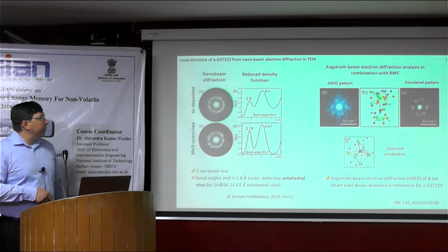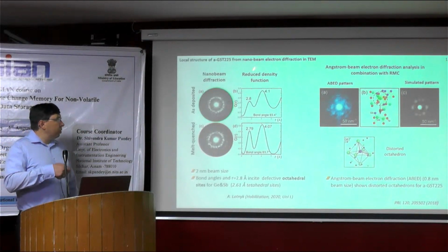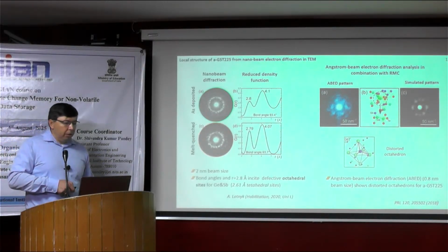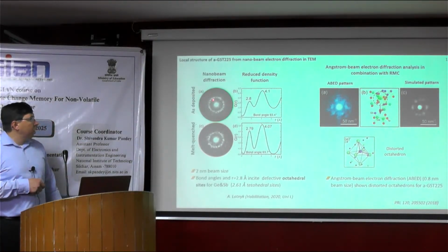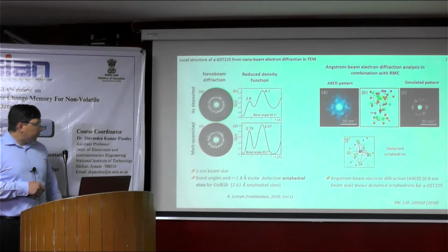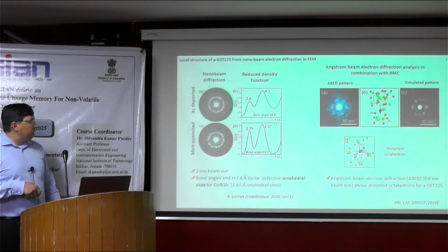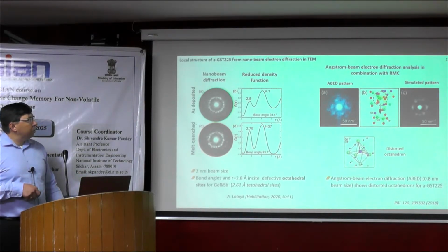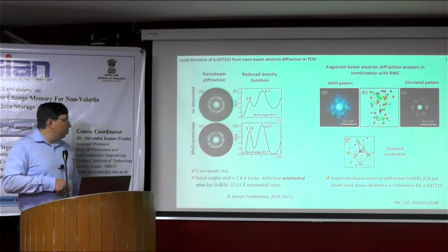You can also study amorphous materials by using RDF, as I introduced before. In TEM, you collect nanobeam electron diffraction and then you can calculate the reduced density function. In TEM, the beam size is very small, you can go down to 2 nanometers.